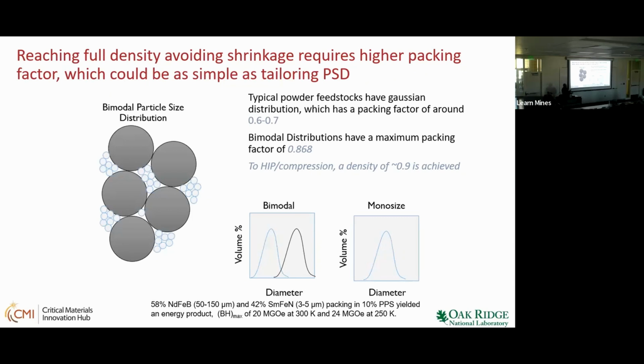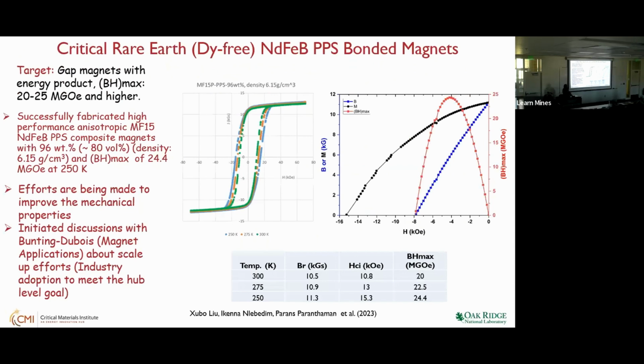So this is an example I'm showing, but you can use this process with any other magnet compositions. You can see the packing density, and you can improve it, and you can anneal, and they improve the mechanical property. So these are advantages we have when we do these printed magnets. We can do post magnetic field annealing, and the energy product is close to 22 to 23.